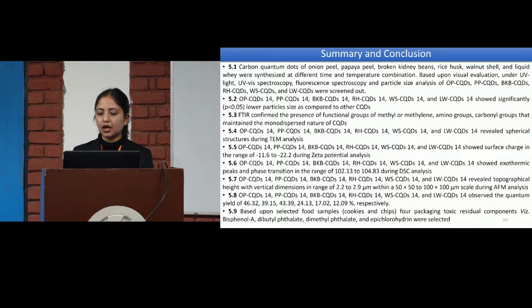FTIR confirmed the presence of functional groups such as methyl or methylene, amino groups, and carbonyl groups that maintain the monodispersed nature of the carbon dots. Those selected carbon dots revealed spherical structures during the TEM analysis, and showed a surface charge in the range of -11 to -22.2 during the zeta potential analysis. They showed exothermic peaks and phase transitions in the range of 102.13 to 104.83 degrees Celsius during the DSC analysis for thermal properties, and revealed topographical height and vertical dimensions in the range of 2.2 and 2.9 micrometers within a dimension of 50 and 100.